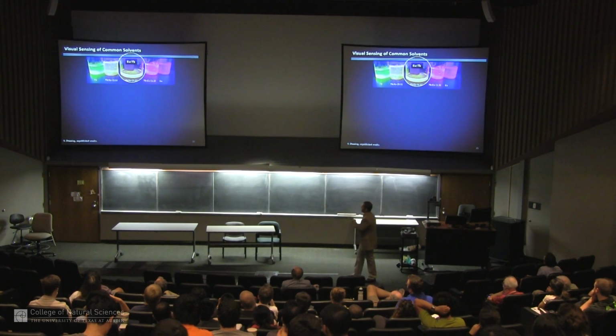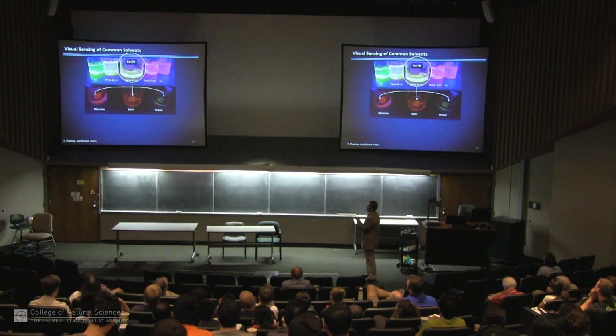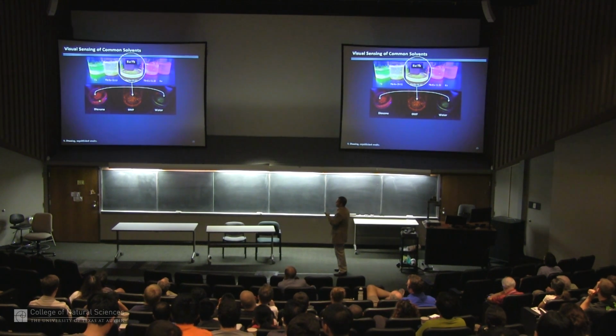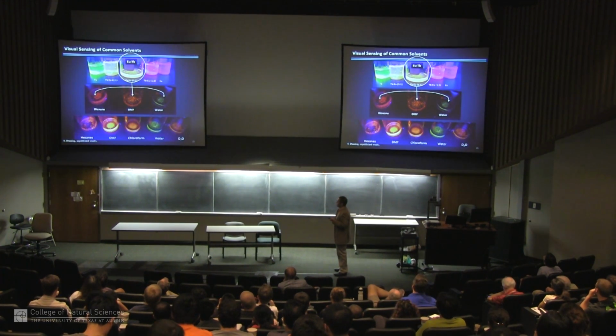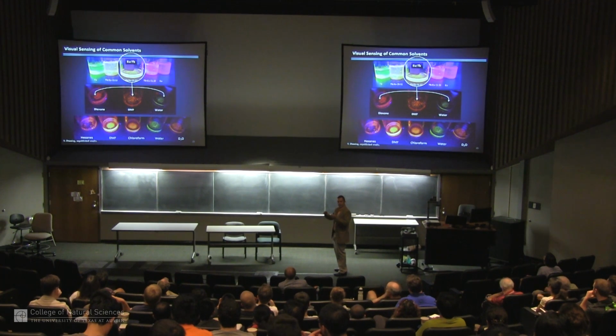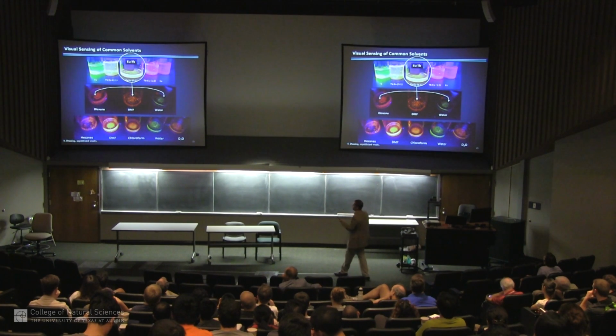This one's interesting. If we take this as a sensor, believe it or not, if you put it in the presence of different solvents, it changes color like a traffic light. And so we can tell if we have this material in something like dioxane, DMF, or water, just by simply exposing the activated crystals. And we can do this with other solvents as well. So it's like a color-responsive dipstick for solvents, and we're trying to now use 2 or 3 different combinations of metals in like an array, so that you can get a coded response to different solvents. So this all works pretty well.